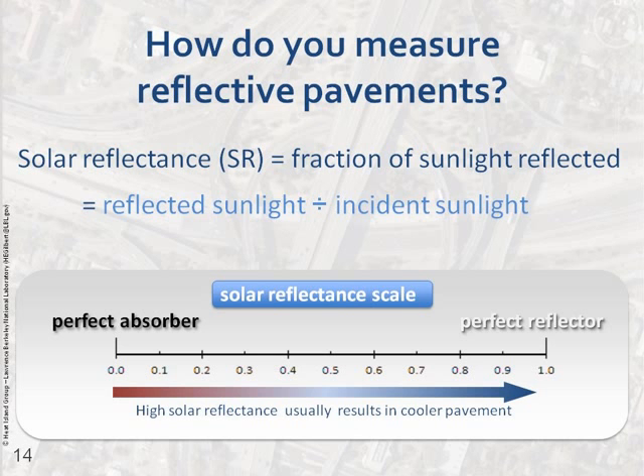So if we think about this in a pavement context, traditional asphalt concrete is usually about 5 to 10% reflective when it goes down, and it's very clean and nice and dark. Over time, as it picks up dirt and the asphalt gets oxidized from the surface, this can actually increase to about 15% reflective. Cement concrete is lighter in color to start and might be 30 to 35% reflective and then degrade over time as it gets dirty.